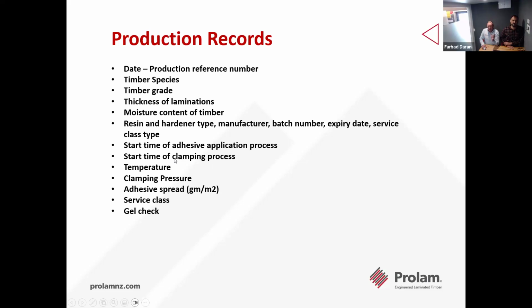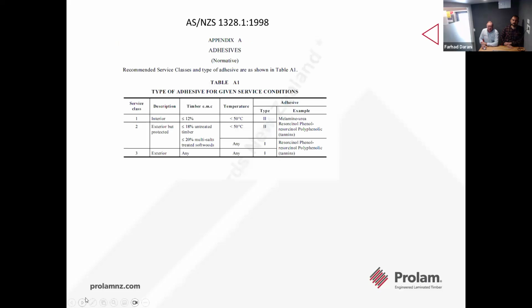So that's quite critical for us because we're using a heat cured glue. So depending on the temperature of the day, we've got to get it into the clamps within a certain time period. So we're taking the temperature as well, clamping pressure, adhesive spread, service class check, and a gel check again to make sure the glue is correct.